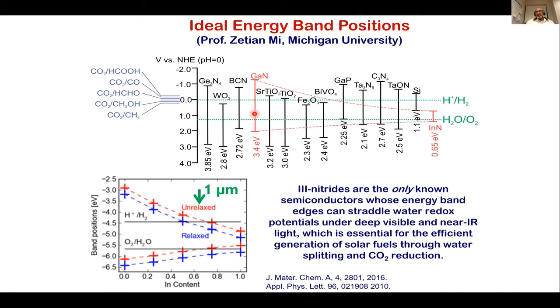So here's a case where you can see that gallium nitride is able to do that, but the problem is that gallium nitride is a large band gap material, so it only absorbs UV light. If you take indium nitride, it only straddles one of them, but not both. So that means it only absorbs infrared light.